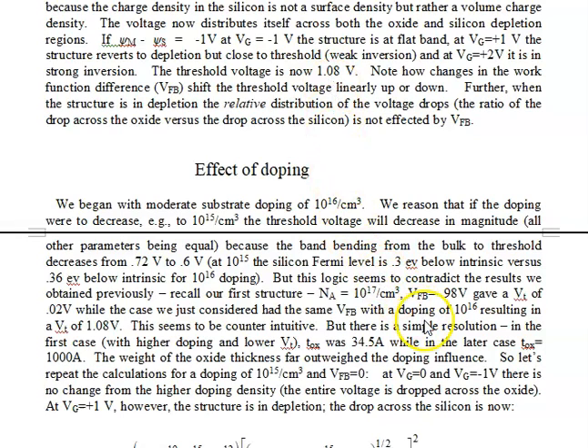So what's the resolution? Well, there's a very simple resolution. In the first case, with the higher doping, 10 to the 17th, and the smaller VT, 0.02, the oxide thickness was extremely small, 35 angstroms, versus the case right here where the oxide thickness was 1,000 angstroms. So the issue here is the weight of the oxide thickness, the influence of the oxide thickness far, far outweighs the influence of doping. So we're going to repeat that calculation now for a lower doping and then for a higher doping, but we'll save that for the next session.